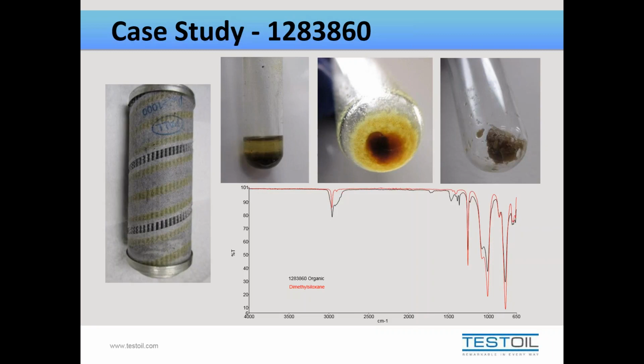But then we also found polyether ester, which meant that a surfactant was possibly filtered out. And surfactants are generally pretty large molecules, so it's not that uncommon that that could happen. And part of the issue is that depleted surfactant in the system could reduce the lubricity of the fluid, which may have been a factor in the failure. So then we also found silicate, which is really just related to dirt. And we also had a little bit of polyethylene terephthalate. But keep in mind that polyethylene terephthalate, or PET, is the same exact material that the filter was made of, or portions of it at least. So that wasn't a very interesting find, other than saying that we had some fibers come out during our washing process of the filter media.